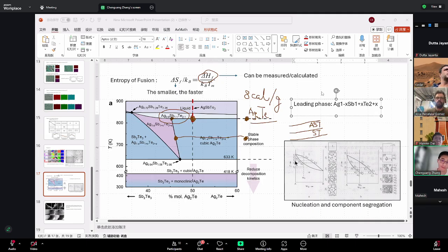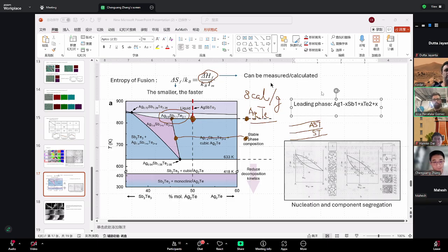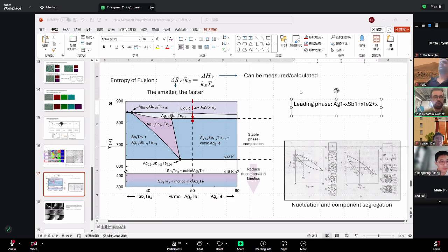Sorry, I'm just curious, why are you saying STEM? Why not EBSD? STEM has a finer spot, right? So in the STEM, you have areas where you have captured very, very well the composition of everything. Whereas EBSD, if you think about it, is still EDS. The composition is arbitrary. What you capture in EBSD is structure. Those points are Kikuchi patterns, they are not composition, right? We have composition data, but it's not very reliable.